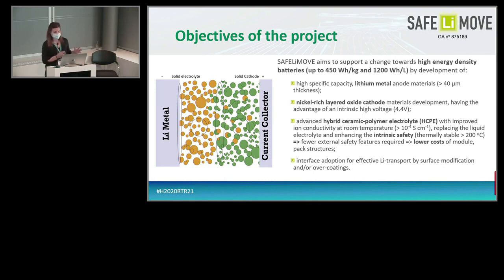Then if we move to the positive electrode, we are developing nickel-rich layered oxide cathodes that have the intrinsic advantage of high voltage. And in order to put everything together, we need to look into an electrolyte that will replace the flammable liquid electrolyte and at the same time allow us to work with these high voltages and also the reactive lithium metal. For this, we are developing advanced hybrid ceramic polymer electrolytes, HCPEs, that will improve the electrochemical stability, but we are also looking for high ionic conductivity, where the target is above 10 to the minus 4 Siemens per centimeter. The intrinsic safety of this electrolyte, with a thermal stability above 200 degrees, will allow us to reduce the external safety requirements at the battery pack or battery module level. In this way, we will also have an impact on the total cost of the battery.